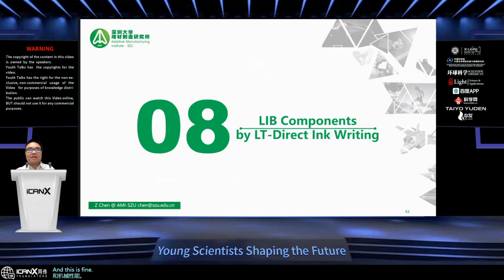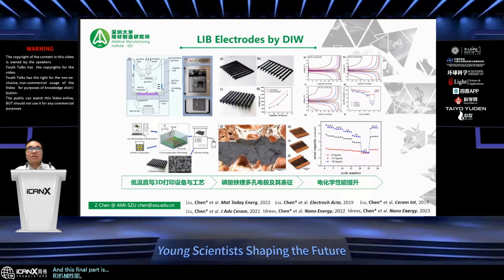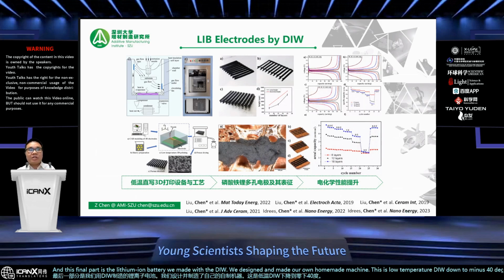And this final part is the lithium-ion battery we made with the DIW. We design and make our own homemade machine. This is low temperature DIW, down to minus 40 degrees C. Then we can keep it, it's like freeze drying. We can keep the pore microstructure, so the mechanical and also the electrochemistry performance can be enhanced.